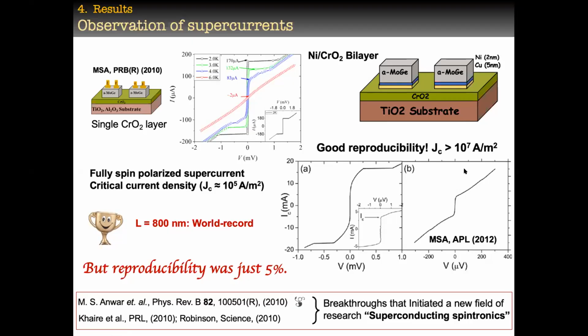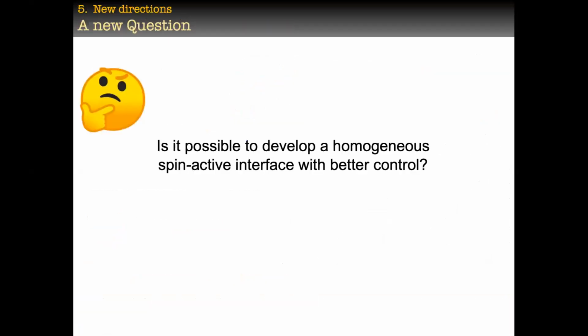In these devices, as I already said, for spintronics we must have a current density of the order of 10^7, which we can achieve with chromium dioxide, and the longest length. The problem is that the reproducibility is very low, so this is not ready for industry. Then we need to think of something else: is it possible to have a homogeneous spin active interface, meaning that the whole device contributes to the generation of spin triplet supercurrent?